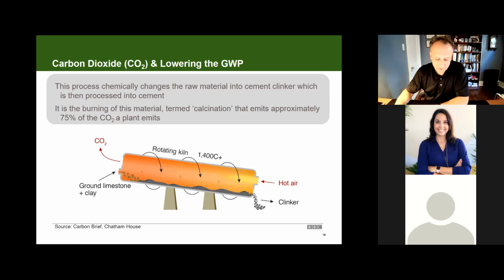Okay, so you can see here the burning of this material is termed calcination, and that emits approximately 75% of the CO2 that a plant emits. So this is really the crux of what we're talking about: creating this hot air to burn up the limestone to create the clinker that creates our CO2.